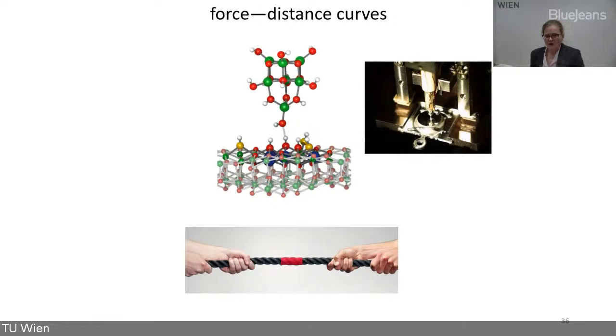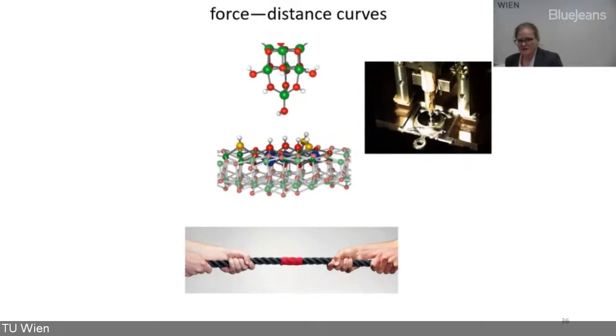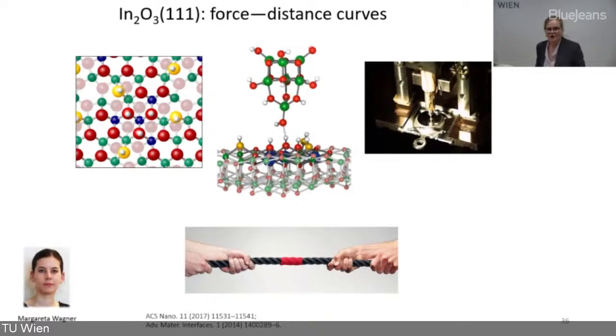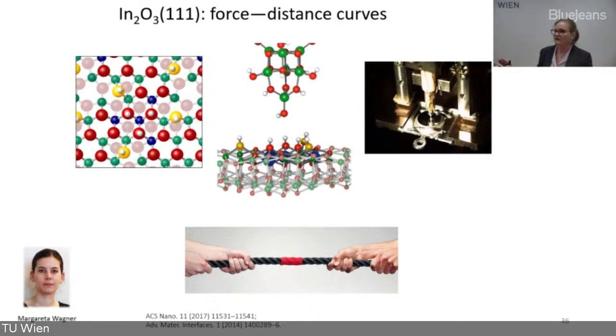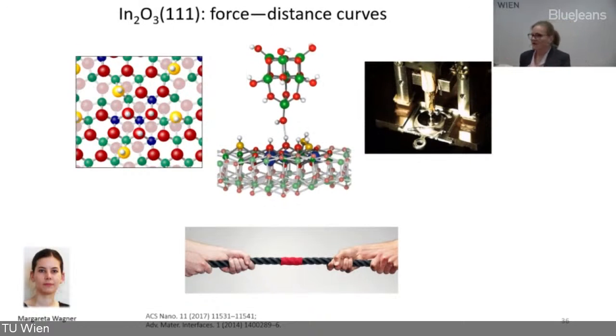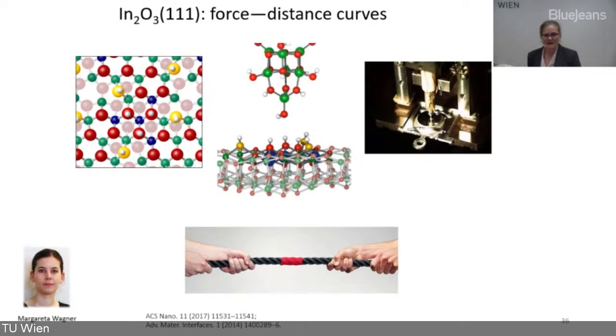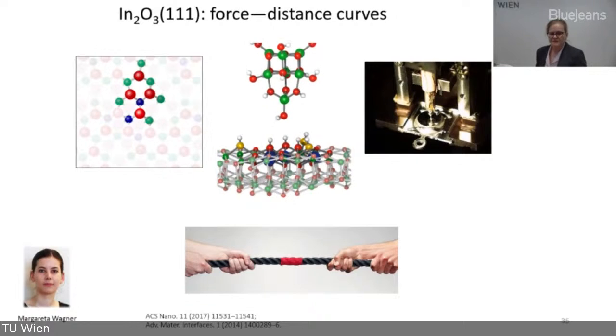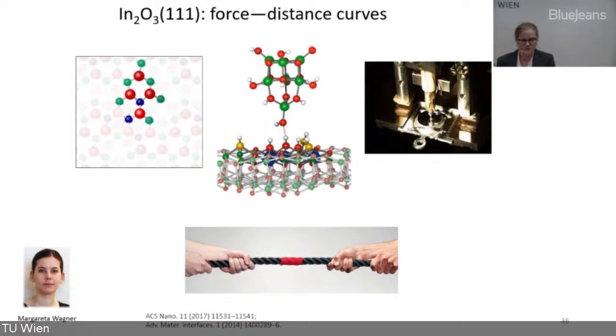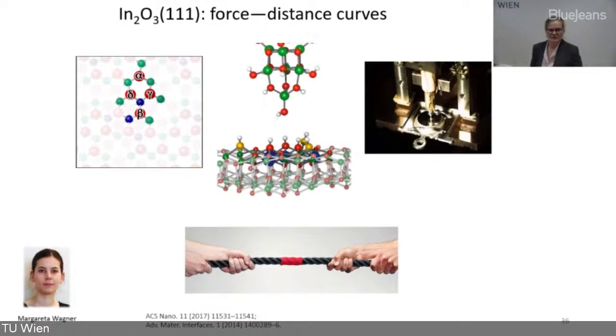The surface drawn here is the one where we did the experiment, an indium oxide 1 1 1 surface. I don't want to go into details - the queen of indium oxide is Margareta Wagner in my group. On this surface there are 4 different types of oxygen atoms, different in the sense that they each have different coordination to their neighbors and different bond lengths.